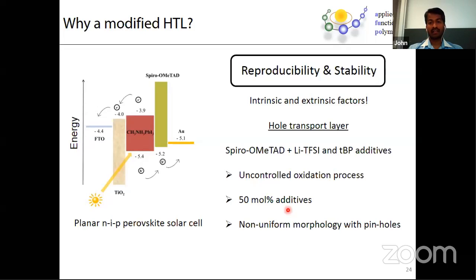And on the other hand, as I said, spiro-OMeTAD is an organic molecule, as we have seen before, and lithium TFSI is a salt. When you mix these two systems, basically a polar or ionic system and a non-polar system together, they phase separate. Since they phase separate, the film quality will be very, very poor. So basically we end up having non-homogeneous or inhomogeneous films with a lot of holes in them. So all these things could cause, or are causing, issues with the device performance over time. And these are the ones that actually cause the problem for reproducibility and also stability.